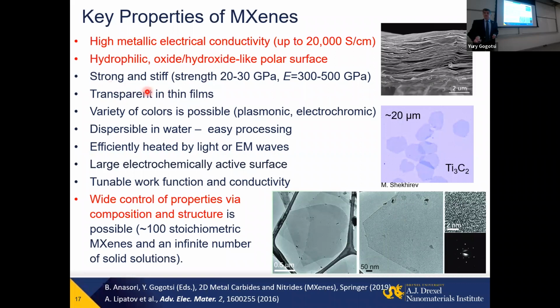But they're also strong and stiff. I'm not going to show you slides, but they're actually stronger than any other solution-processed material. If you take a single flake of graphene separated from an ideal perfect crystal, or boron nitride, they will have a higher modulus and strength. But every other material, including reduced graphene oxide, will be weaker. And this allows something that is a direct consequence of this, but not obvious. We can make, in solution processing, flakes go into, say, 20 microns and larger.